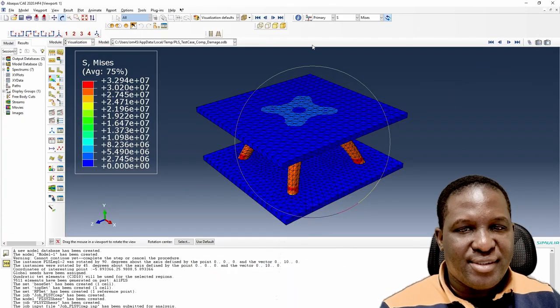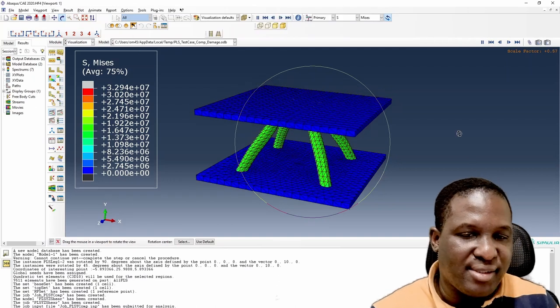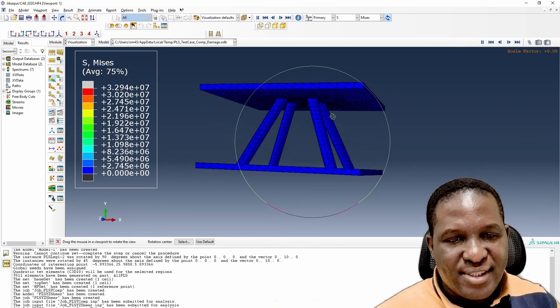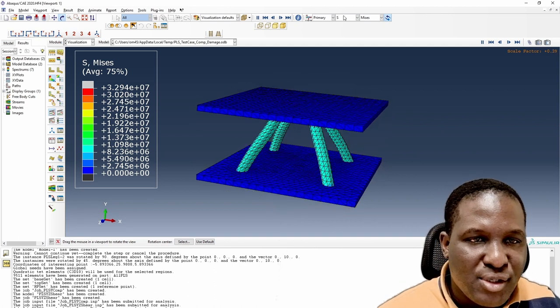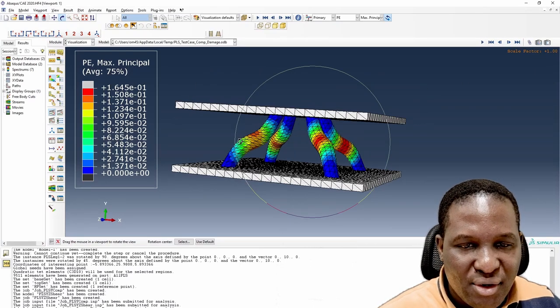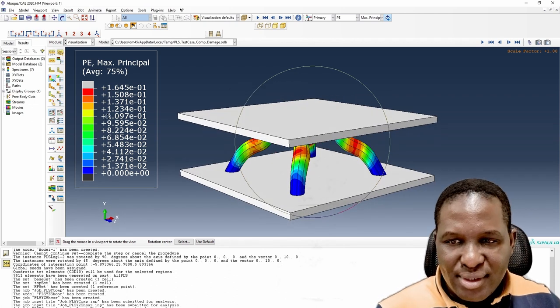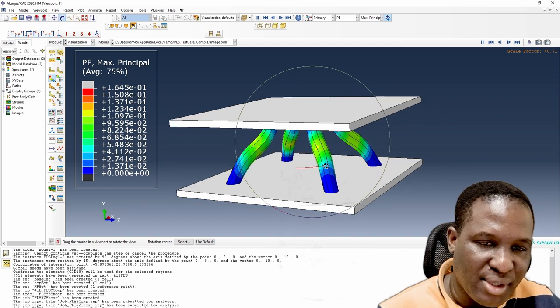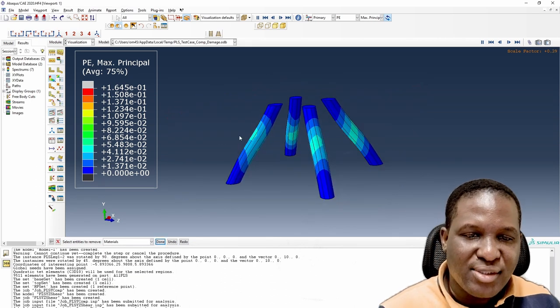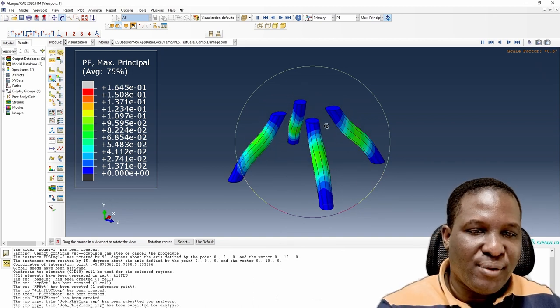The first result is the Y compression. In terms of von Mises stress, we get a nice concentric uniform compressive behaviour about the centre line. If we increase the scaling factor, you get this kind of result. Looking at the plastic strain, you can see a lot of plasticity and buckling happening right on the struts during compressive behaviour. Taking away the mesh, you get a nice result showing what's happening in all directions. If we hide the face sheet material and look only at the struts, you can see how the deformation is going on.